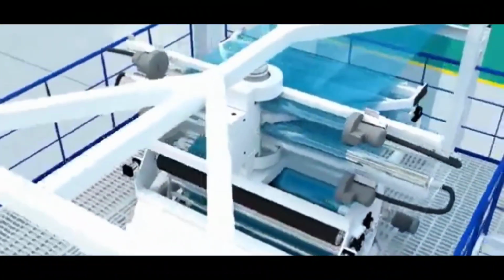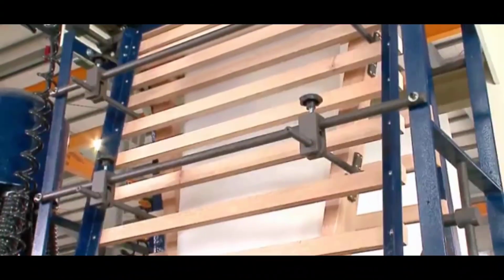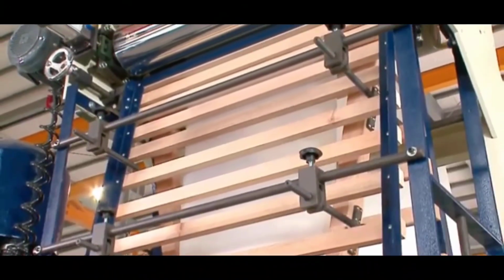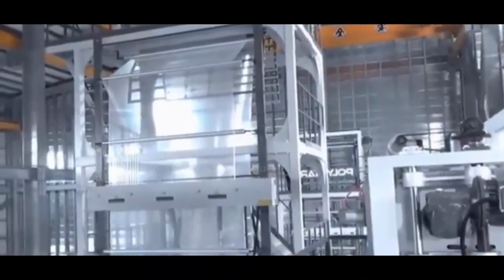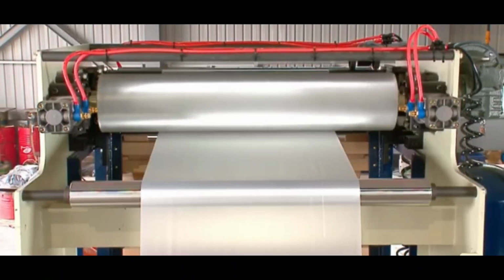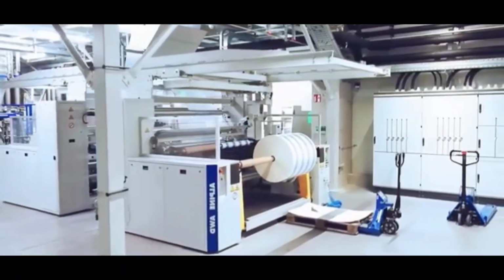This roller system not only winds the film, but also stabilizes the surface and evenly distributes stress across the full width of the material. Each roller is locally heated or cooled to maintain consistent temperature, preventing shrinkage, adhesion, or surface wrinkling. A temperature difference of just a few degrees Fahrenheit can cause deformation or reduce clarity.